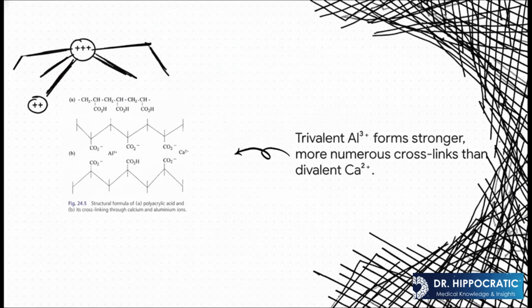This difference in charge, or valence, is the real secret to the material's final impressive strength. And this diagram shows us exactly why that charge is so important. A calcium ion with its 2+ charge can link two of those acid chains together. But an aluminum ion with its powerful 3+ charge can grab onto 3 acid chains. This creates a much denser, tougher, and more rigid structure. This is the maturation process, and it happens over the next 24 hours, building the cement's real, lasting strength.